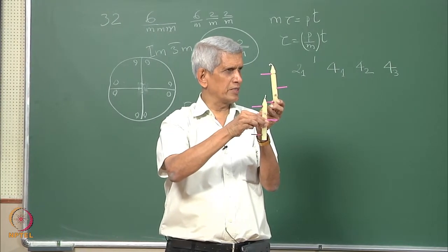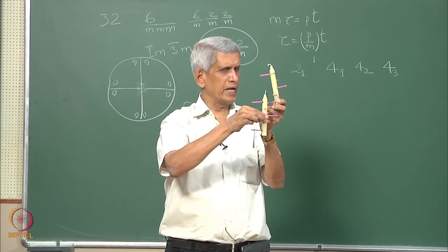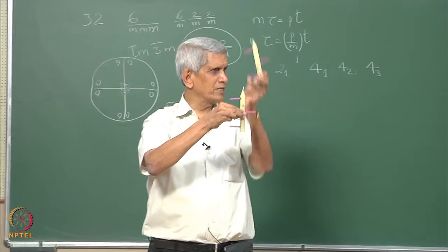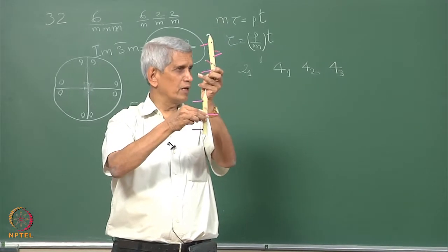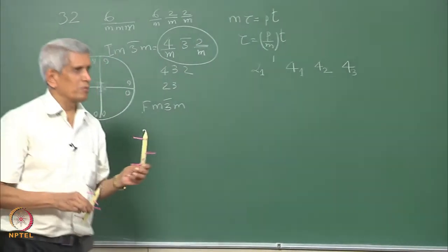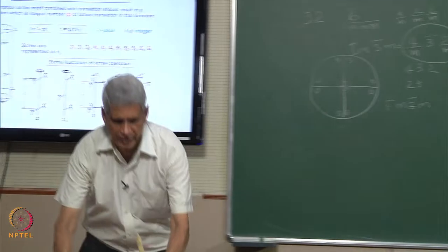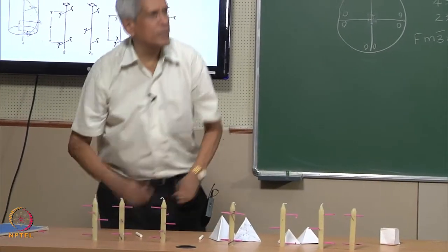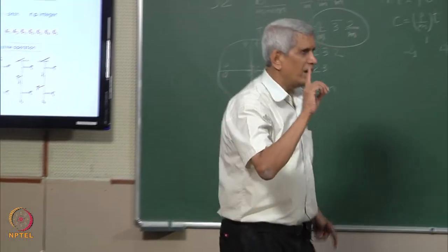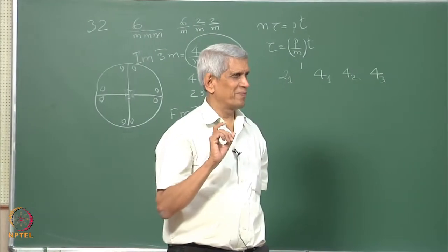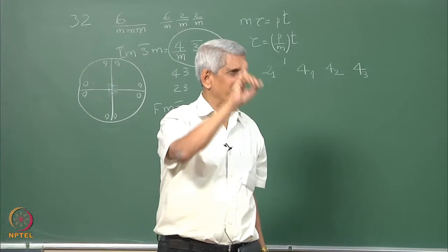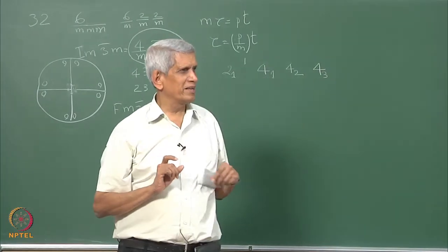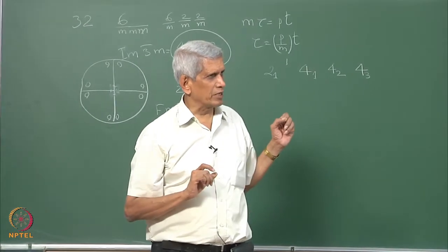With respect to this, if I rotate it in this direction, 1/4, this is equivalent to 1 minus 1/4 in the opposite direction, okay, that is how it is being considered. So essentially this is equivalent to, if we take a pitch of 3/4 and then take it along, okay, then we will notice that this will turn out to be identical to it. Okay.